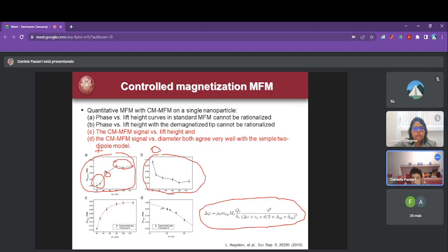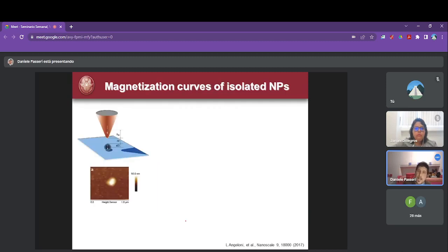Also for particles with different diameters. So basically, with these results, we realized that in this case, it was not the model that was wrong. It was the experiment. And what we did with this, for instance,